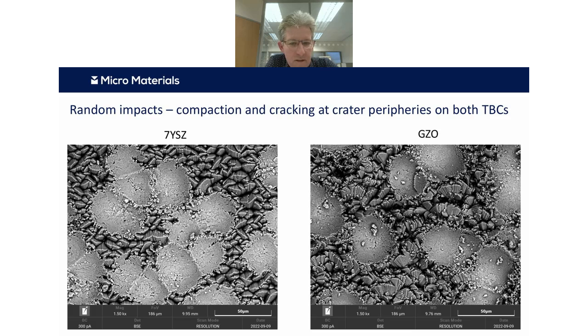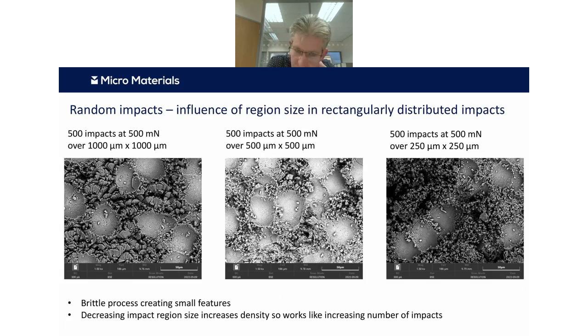Just at the beginning of the test, you can see these things. They look quite similar. The same sort of mechanism occurring in both cases. What's interesting, though, is if we increase the severity of the test by either doing more impacts, or in this case to do the same number of impacts but over a smaller region. So in this case, I'm contrasting 500 impacts either over 1 millimeter by 1 millimeter or 0.5 millimetre by 0.5 millimetre, or 1/4 millimetre by 1/4 millimetre.